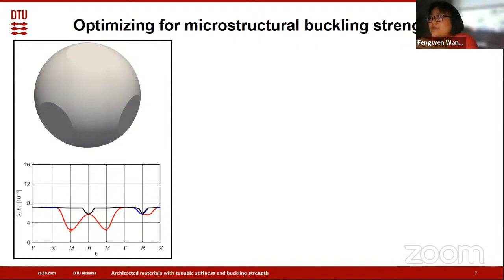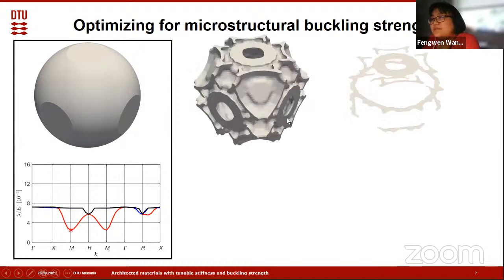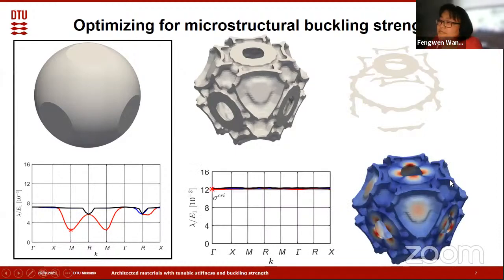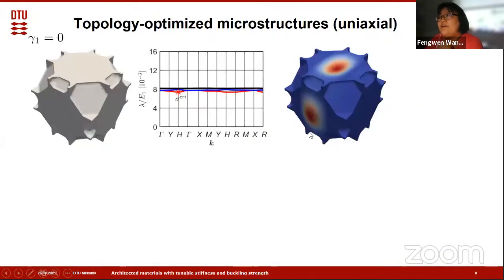As a first case, we try to optimize microstructures with maximum buckling strength under hydrostatic loadings. This is the initial design. This is the optimized blueprint. And this is a slice view. We can see the optimized microstructure does possess a well-defined lens skew. This image shows the band diagrams of the optimized structures, and this shows the corresponding critical buckling mode. We can see that compared with the initial guess, the material buckling strength has been significantly enhanced.